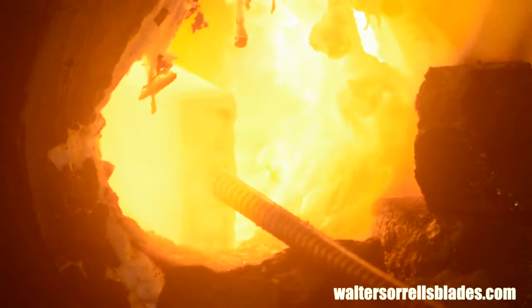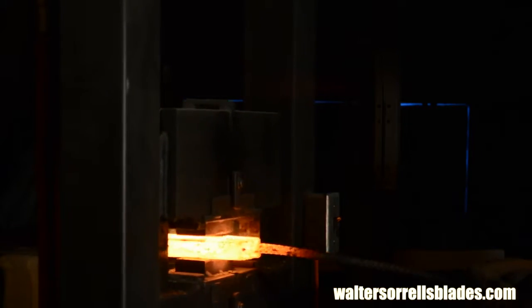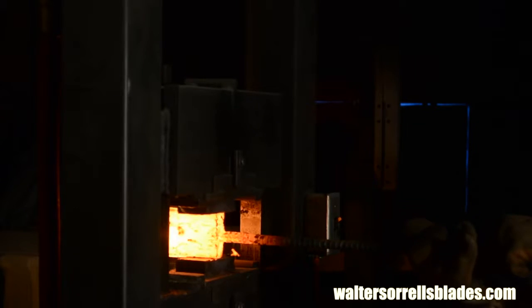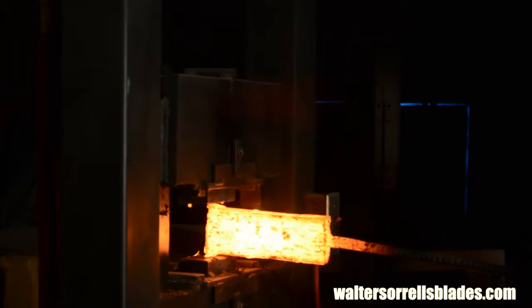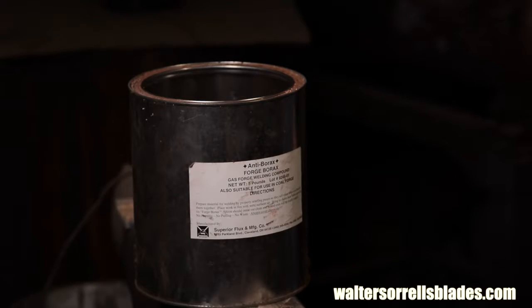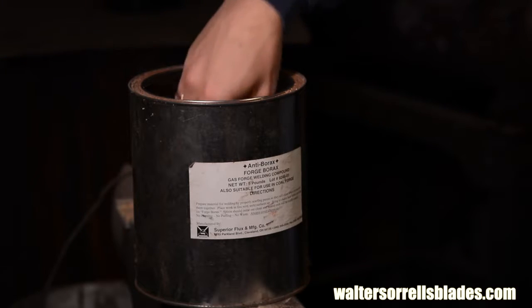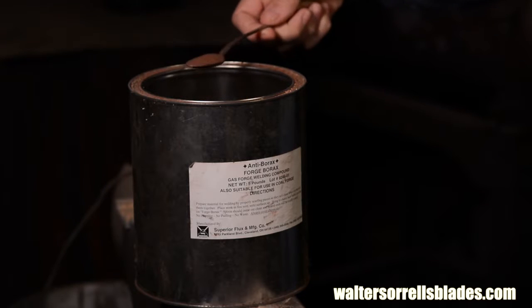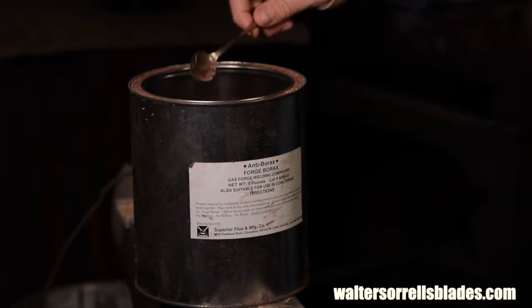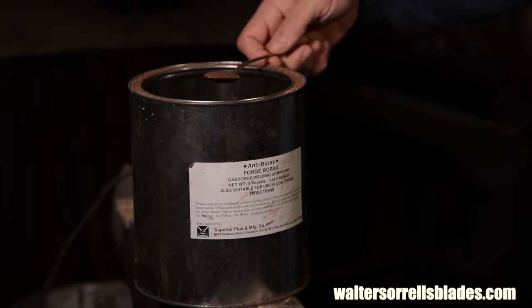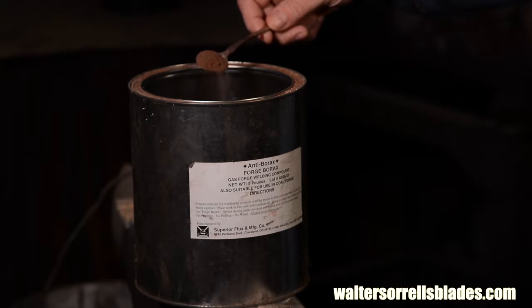Now, we haven't mentioned flux yet, so let me go into that a little bit. The function of flux is to dissolve the constantly forming layer of oxide off the steel so that when you squash the billet together, you get perfect steel-to-steel contact between clean steel. I use anhydrous borax as a flux, also known as forge borax or anti-borax. You can buy forge borax from blacksmithing supply places, but 20 Mule Team borax from the grocery store will work fine too. The only difference is that there's water in the grocery store borax.